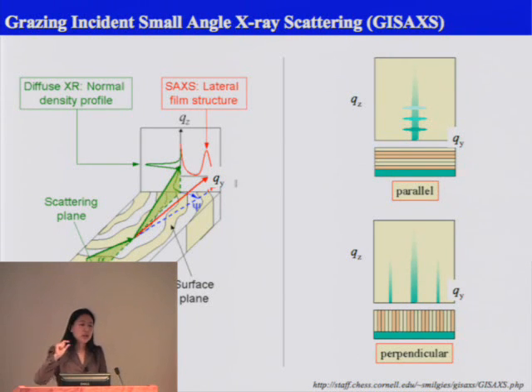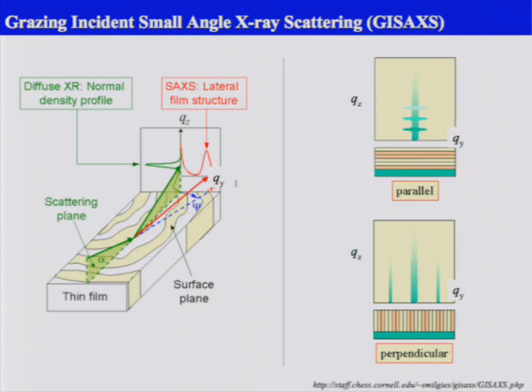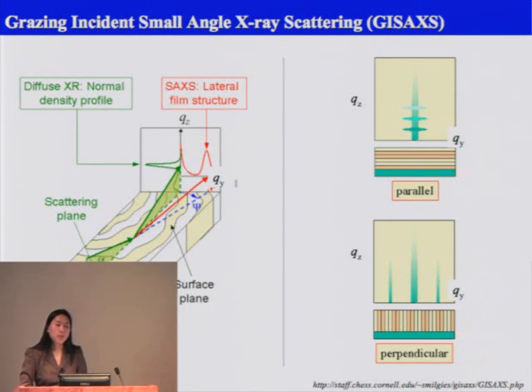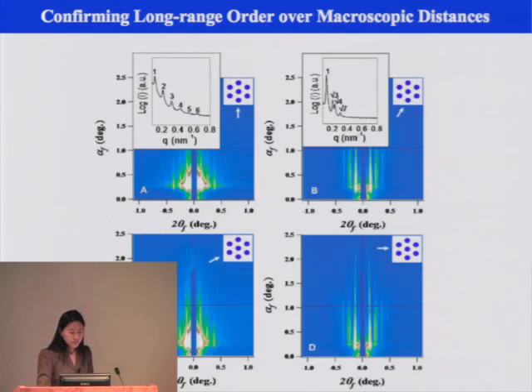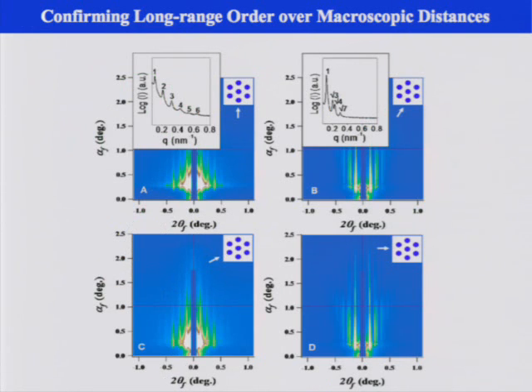By the time you do it at 0.1 or 0.2 degrees, the spread of the beam, or what we call the footprint, on the sample can extend to about 1 or 2 centimeters in distance. That means what you are collecting in your detector is going to reflect the ordering information for the area you are looking at, which is about 1 to 2 centimeters. So that allows us to probe the ordering of the block polymer over a large distance. You need to follow with me a little bit.